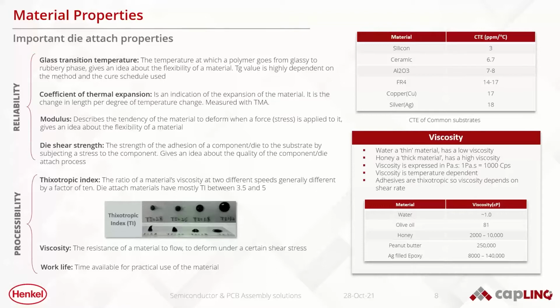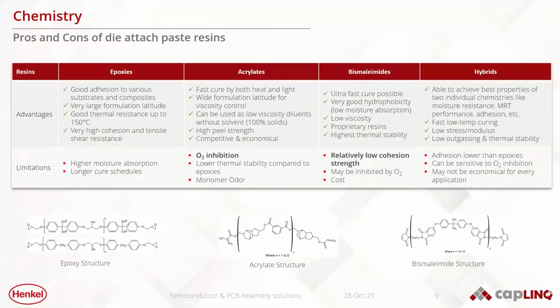If we take a look at other material properties, they're geared more towards the processability, being able to use that paste in their package. The two main properties, namely thixotropic index and viscosity. Thixotropic index is, the higher the number, the more that the material will keep its shape after it's been dispensed out of the syringe dispense. Viscosity, on the other hand, is about the fluidity of the material. It's how well the material flows. If you take a layman's example of peanut butter, it might have a viscosity of 250,000 centipoise, and water has roughly a viscosity of 1 centipoise, then a silver-filled epoxy die attach material might have a viscosity between 8,000 and 140,000 centipoise.